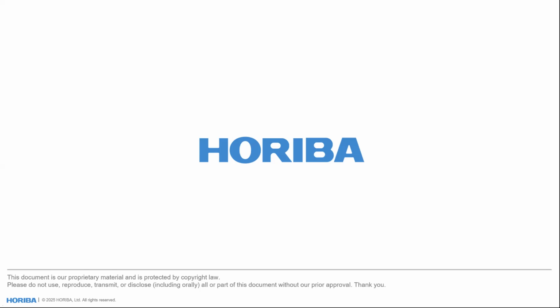Okay. I actually answered this question during the presentation, but we can go down to 150 microns inside the sample. So the depth is a maximum of 150 microns, and we can identify different layers within the nanometer scale. The depth resolution is like 5.4 nanometers, and the maximum depth we can go is 150 microns.